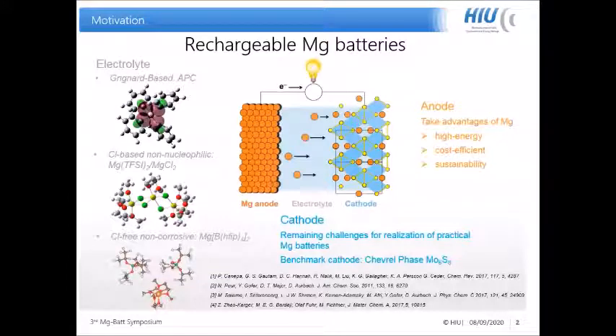The fact is that even back in 2000, we already had our first benchmark cathode, the Chevrel phase molybdenum sulfide, as reported by Doron Aurbach's group. But 20 years later, it's still the only benchmark cathode that we are using. So we are still struggling to find a proper cathode which can reversibly insert and deinsert magnesium at room temperature, I would say. And at this stage, the cathode has been a bottleneck issue for realization of a practical magnesium battery.